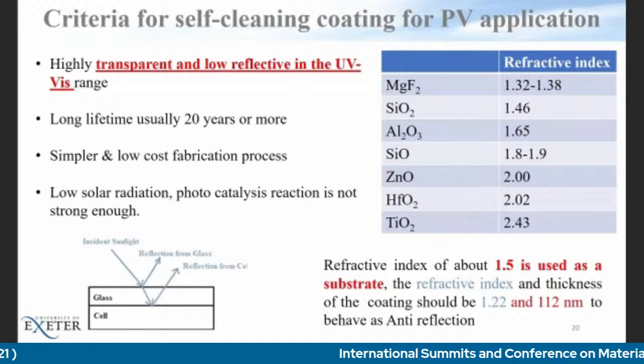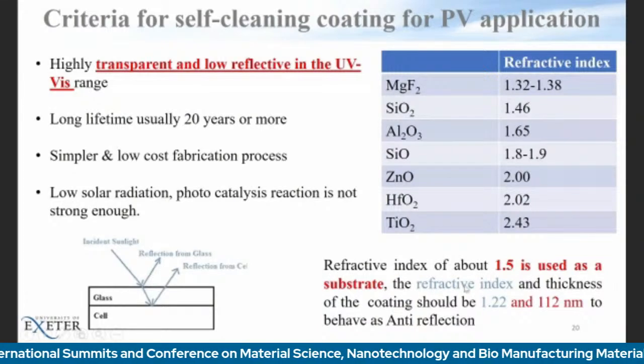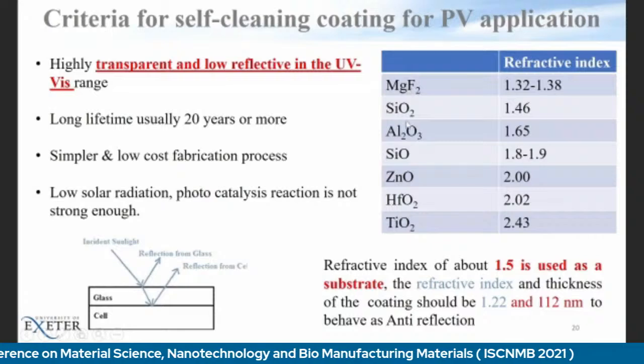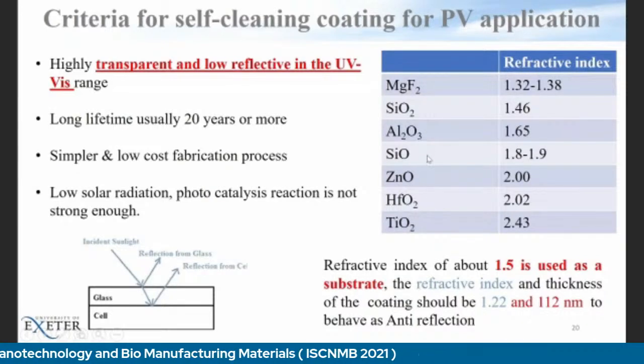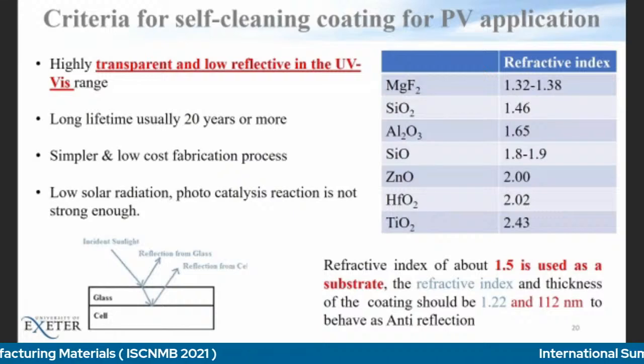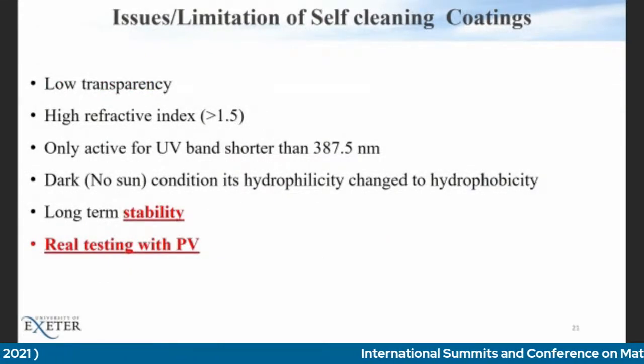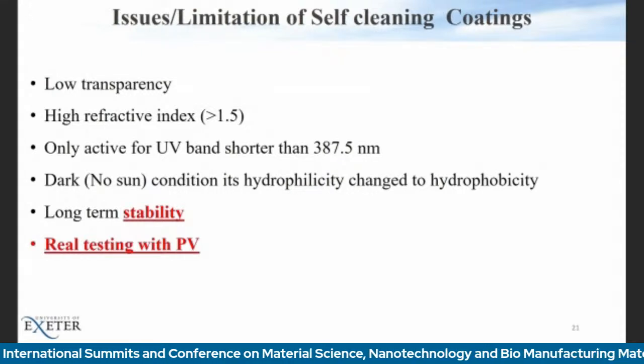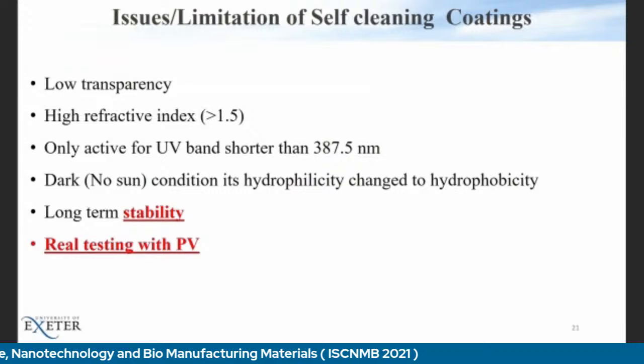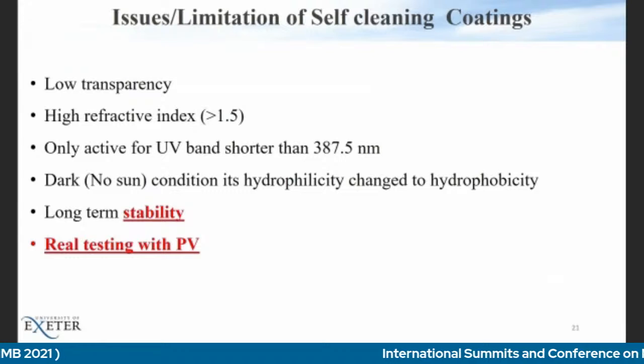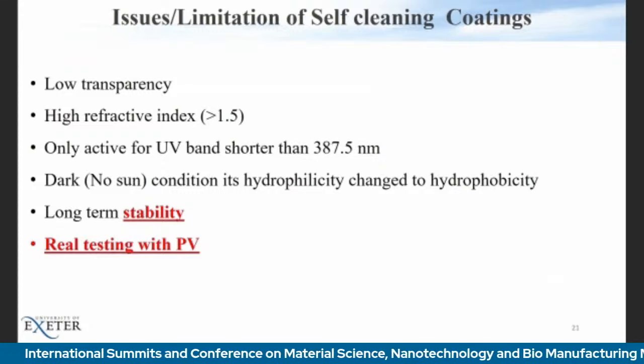But honestly, we are not very close to this, because a coating should have all those values. Generally, the currently available coating materials have a very high refractive index, but we are trying to find some solution to this problem. So the current limitations are the transparency, the refractive index, and that they are only active in the UV band. If there is no sun, they generally don't work properly. There is also an issue with long-term stability. And most people working on self-cleaning don't really test with PV technology. They just manufacture it in the lab and say that they have created a self-cleaning technology.